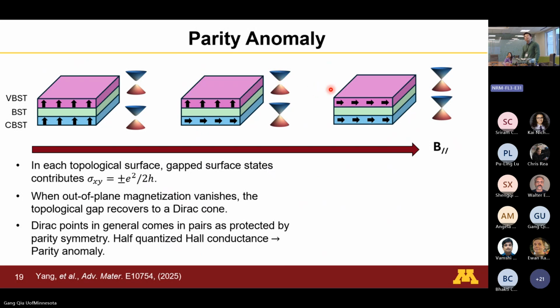Okay, and then if you keep increasing the in-plane field, both layers become in-plane. Now you have 2 Dirac cones, right? So this basically recovers a classical Dirac topological state. Now this is a very unique situation in the middle right here, right? So if you take any Dirac materials, the Dirac points always come in pairs. You cannot create a single Dirac cone, right?